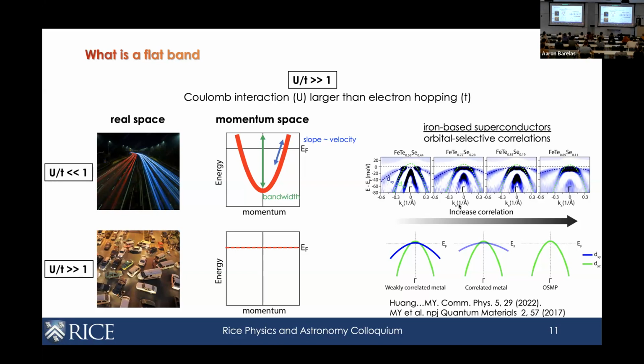And that essentially is direct evidence that the correlation, or electron-electron interaction, is becoming stronger as you go from this end to that end, which is exactly described by this process. So in this example, we discovered that if you keep going, you will eventually enter what's called an orbital selective Mott phase, where that band becomes completely localized and flattened, and then it's no longer there. Anyway, these are some of the results that we published last year.